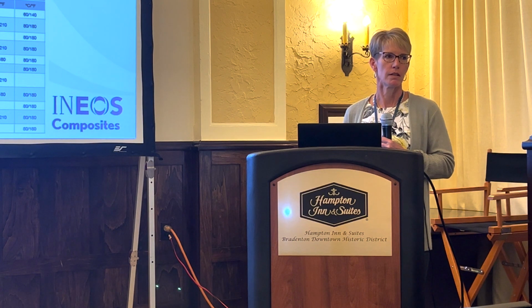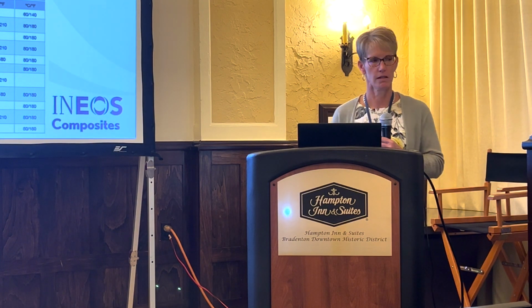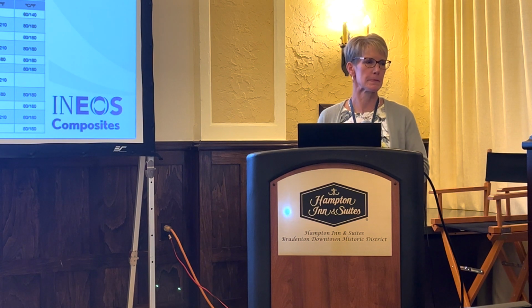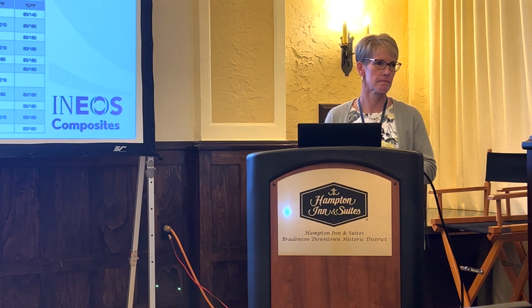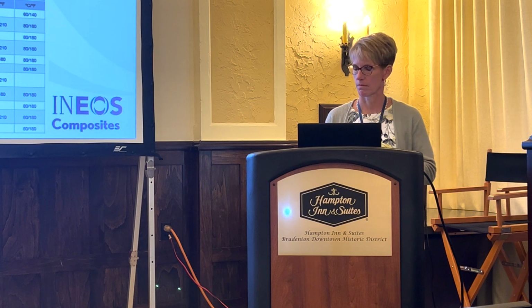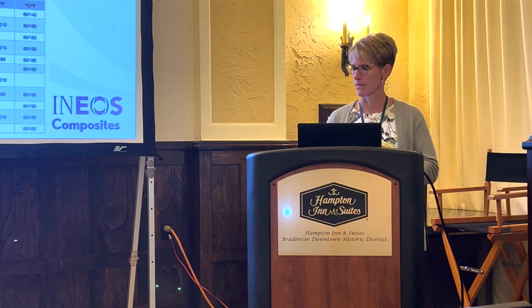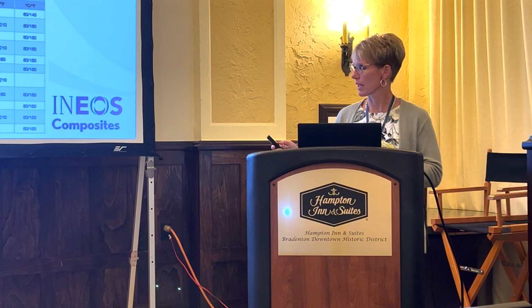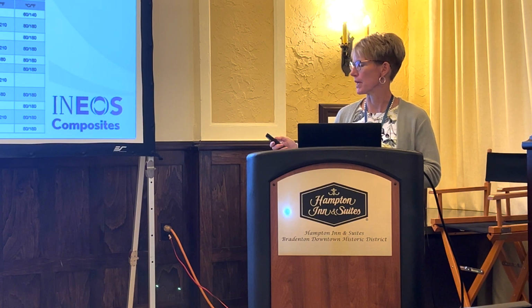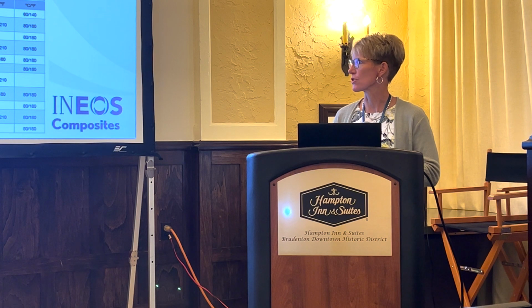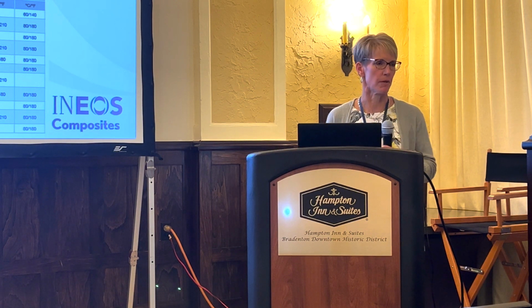Concentration and temperature are important. That all plays into the recommendation. What's the lifetime for that FRP? If it's ambient temperature and 20 to 30% concentration, you're probably going to get 15 to 20 years. In our selection guide, which is either online or you can get a hard copy, we do list the concentrations. So as Mike said, in HF, that's probably going to go up to only about 30%. Good.